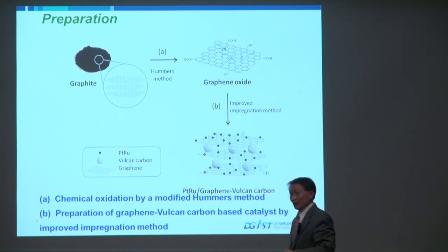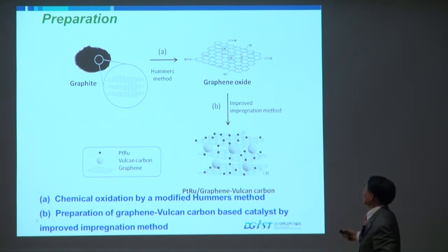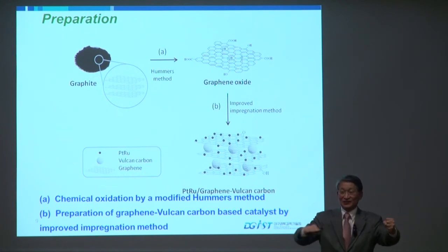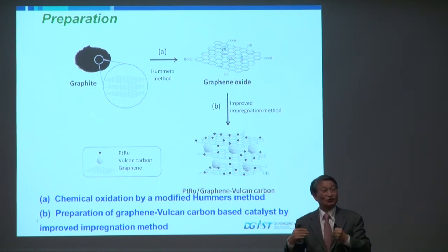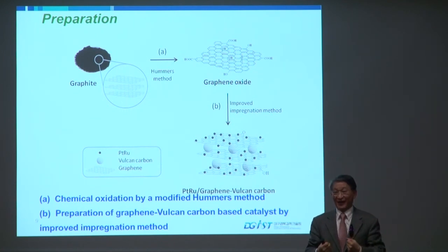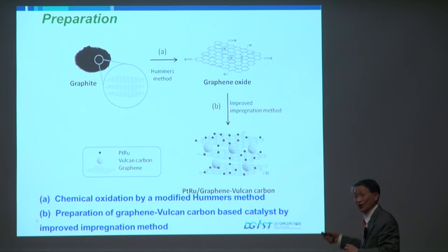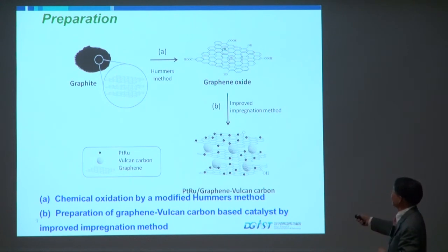So, how about introducing Vulcan carbon with graphene nanosheets? We can assume that if the Vulcan carbon, activated carbon, stays in between the sheets, the layers of the graphene, then we can utilize all surface areas, and we have enough channels for mass transport. So that's why we prepare this structure.